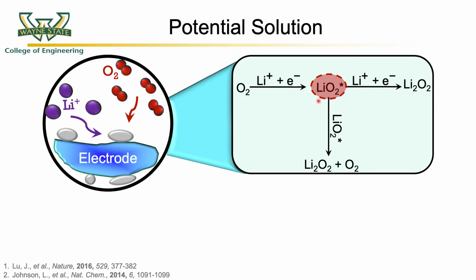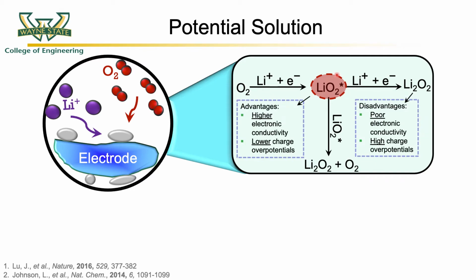Recently, it has been reported that LiO2 can be formed as a stable discharge product in these battery systems. One advantage of stopping the reaction at LiO2 as opposed to going to Li2O2 is that LiO2 offers higher electronic conductivity, resulting in lower charge overpotentials, while Li2O2 results in poor electronic conductivity as well as higher charge overpotentials, as I showed earlier.